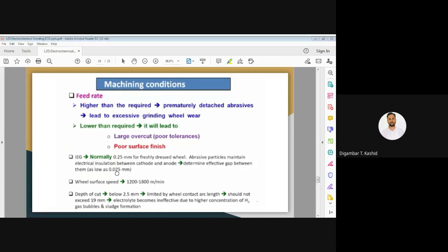Then another is the inter-electrode gap. The gap is generally 0.25 mm for a freshly dressed wheel. Abrasive particles maintain the electrical insulation between your cathode and the anode, and determine the effective gap between them, that is the 0.25 mm gap. The wheel surface speed you have to maintain is 1200 to 1800 meters per minute, and the depth of cut we have to maintain below 2.5 mm, limited by the wheel contact arc length. It should not exceed 19 mm.